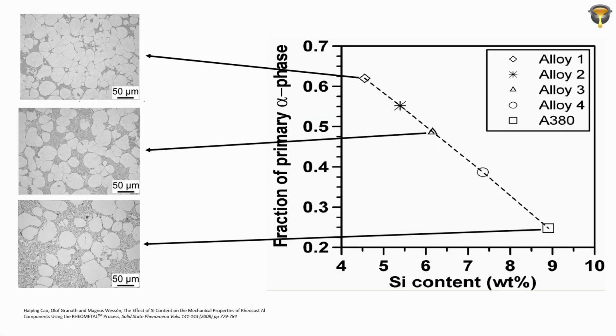Yeah. But it also means, when we're talking about needing 35% solid fraction to have that laminar fill, that we need to pre-solidify 35% of our alloy. And when you're taking, for example, an AlSi10, you are so close to the eutectic point that your solidification interval and your primary alpha phase are not enough to get to that 35%. So you need to be, when you see it in the graph, below 7.5% or 8% of silicon to get to a 35% solid fraction. Otherwise, you're pre-solidifying the eutectic phase, and then when the eutectic reaction starts, everything solidifies, and you don't really see any of the aspects of Rheocasting.